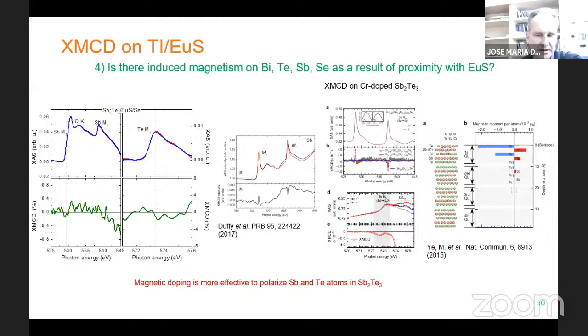I think it's an indirect way to study this interface phenomena, because if you have very well characterized the contribution of your top surface with this weak anti-localization effect, then if, for example, you put a ferromagnetic insulator on top of that, you know it's not going to contribute to the transport, but if you modify your weak anti-localization signal, you can indirectly extract information of what's going on at the interface. So it's just an idea.